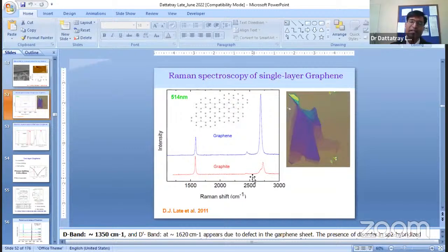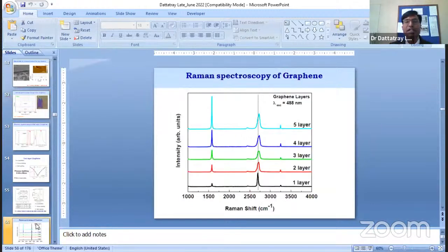Also, you can look at the fitting of this particular peak. You are able to fit only a single Lorentzian. You can see here there are multiple peaks in bulk or in more than 2-3 layers. Now, going from 1-layer graphene to 2-layer graphene, you see the intensity of the G band and 2D band is nearly similar, and you can see here the 3-layer, 4-layer, and 5-layer graphene. So you can continuously monitor these graphene layers.